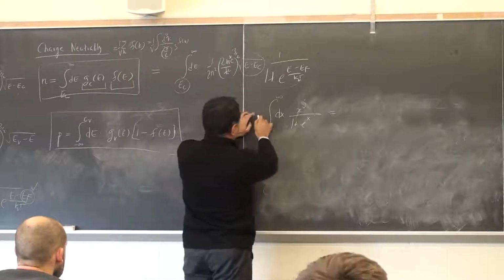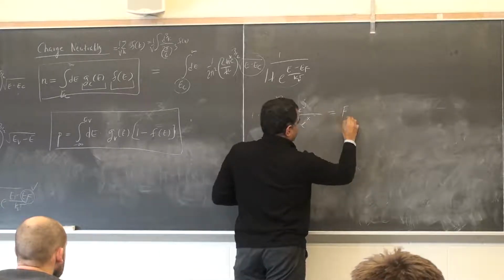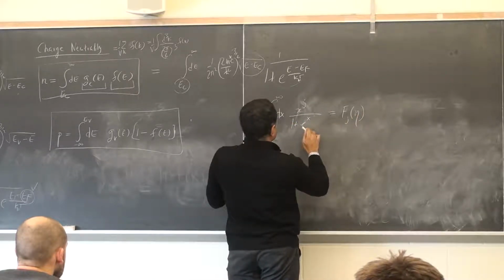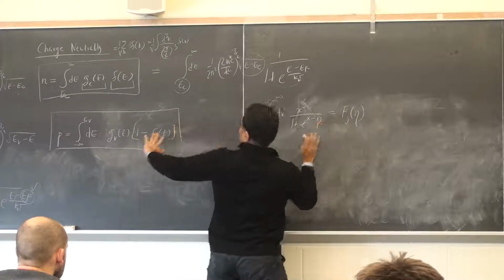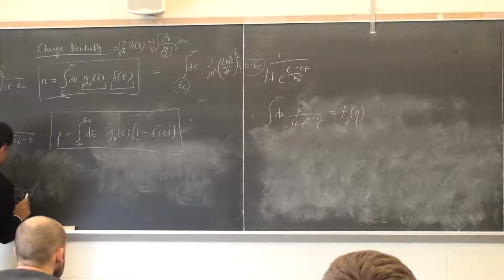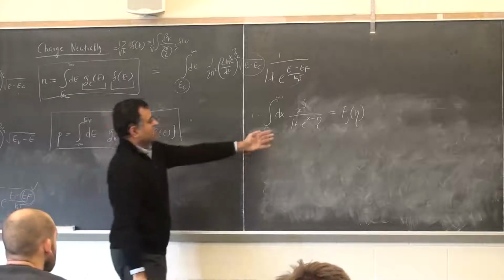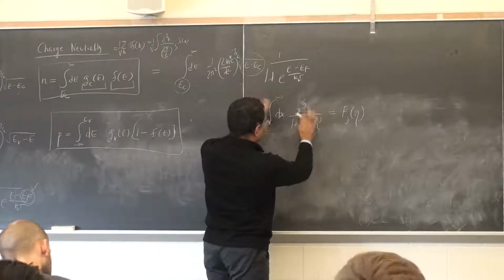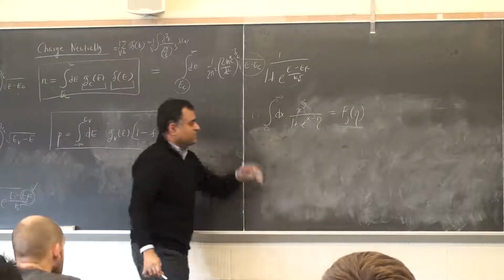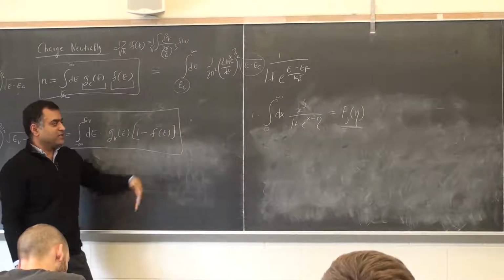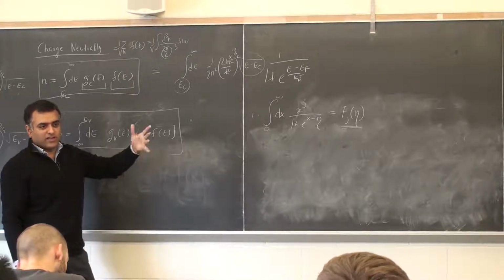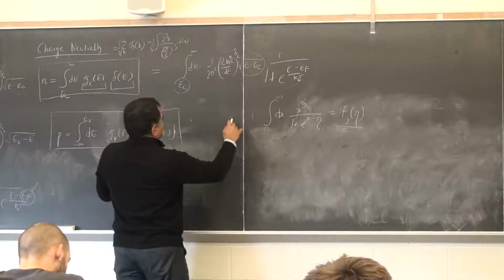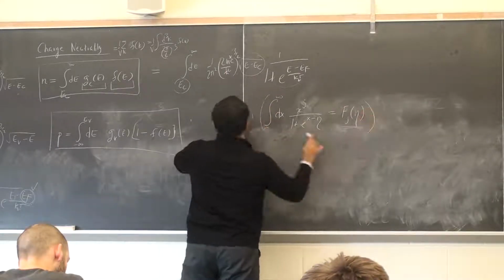Sometimes there are a couple of things in front, but generally this sort of integral is tabulated, with e to the power x minus eta in the denominator, where eta involves the Fermi level. This is a very general mathematical integral. It's not exactly doable analytically, but these are tabulated, and Mathematica or MATLAB know these functions. They're like polylogs and all that stuff. There's no analytical form.